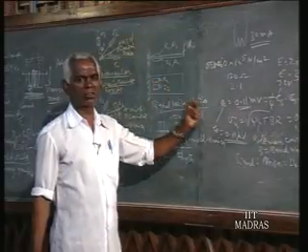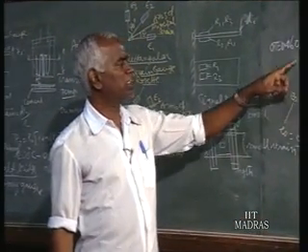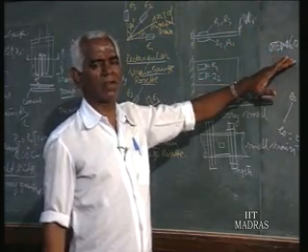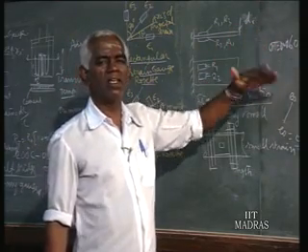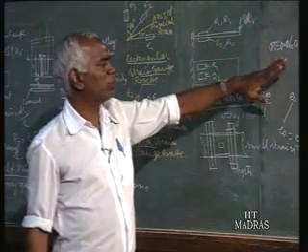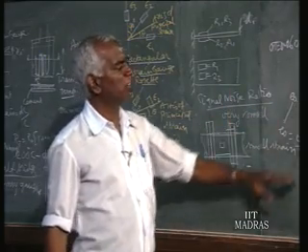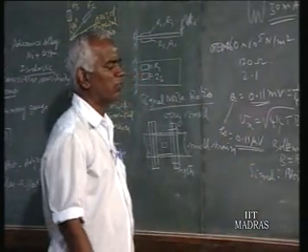That's why we should not paste strain gauges on any existing machine. Suppose we want to find the stress or strain in an automobile part which has been designed already for strength; there we should not paste the strain gauge. That part you have to remove, put in a weaker part and paste it, then you will have sufficient stress and strain. You are deliberately weakening the part, but the weakening should be done below the yield stress. If you go to the plastic region, then it is plastically deformed, and it will spoil the whole thing. So within the elastic limit, you have to weaken the part and then paste the strain gauge, so that we can have sufficient signal to noise ratio of the order of 244:1.